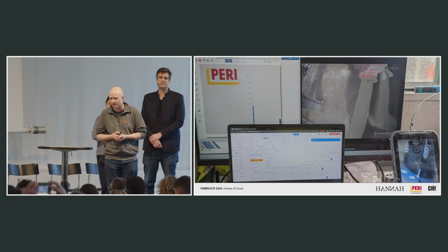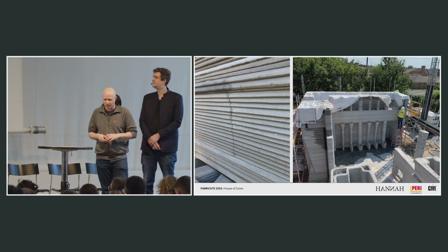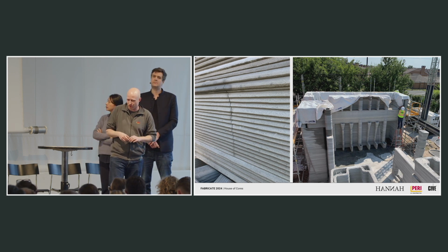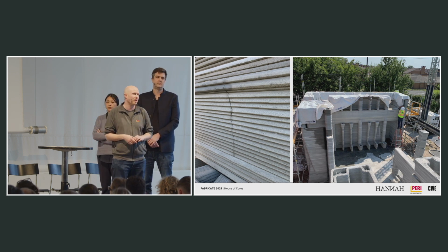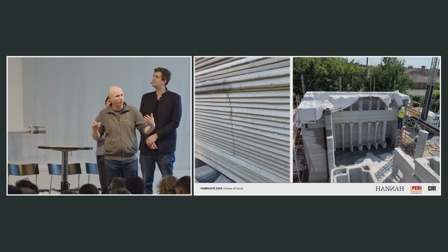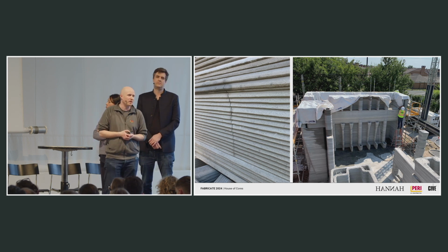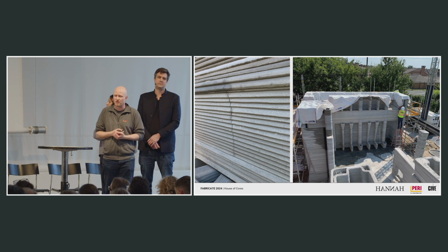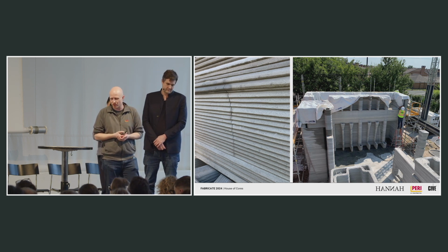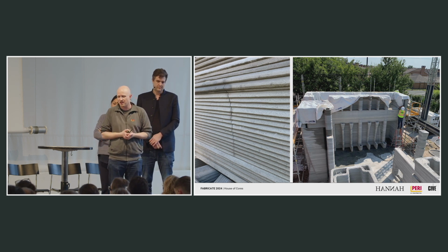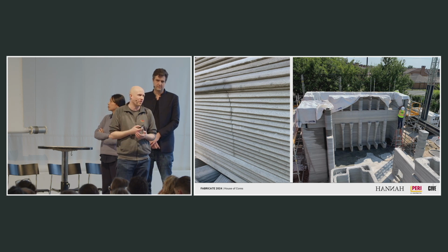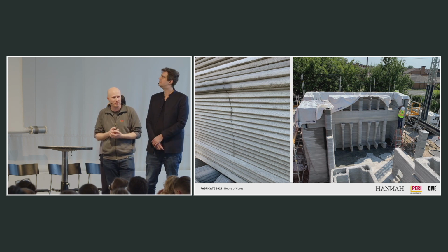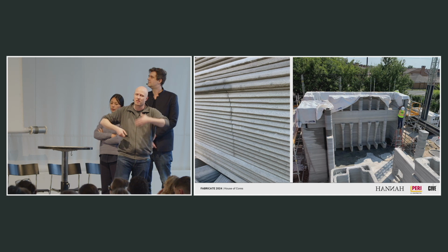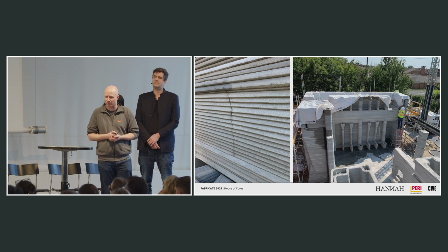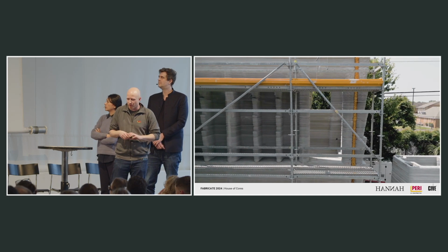Cracking is, for all of you that have printed concrete, an issue, but here we've dealt with it in several ways, where we included expansion joints that are very important in the 3D printed structure, as well as using different curing techniques, as well as, should a crack form after all, certain mitigating measures to ensure that the crack doesn't propagate through the structure.